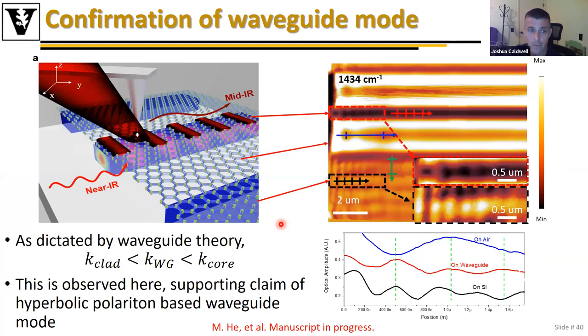And so we can therefore look at creating waveguides here, and I'll just show these very quickly. This is actually work with Sharon Weiss and Dmitry Basov, where we took silicon photonic waveguides that are used in the near infrared and transferred hexagonal boron nitride onto the surface that can support hyperbolic phonon polaritons in these modes. And what we found is that the hyperbolic phonon polariton is entirely guided by the underlying silicon structure. And so without fabricating the boron nitride at all, we can now induce the hyperbolic phonon polariton to follow the same trajectory as the near infrared light. But now because we're using a polaritonic mode, we can shrink that wavelength down so that it's commensurate with the modal wavelength inside the silicon waveguide in the near infrared, despite the large free space wavelength transitions.